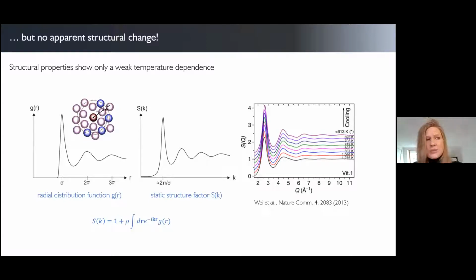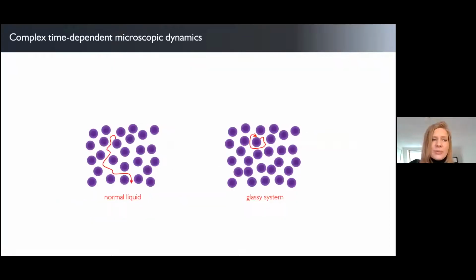And so that means there's essentially a disconnect, an apparent disconnect between structure and dynamics. And that really lies at the heart of the glass transition problem, that the structure on the one hand remains almost the same to that of a normal liquid, yet the dynamics slows down by more than 15 orders of magnitude.